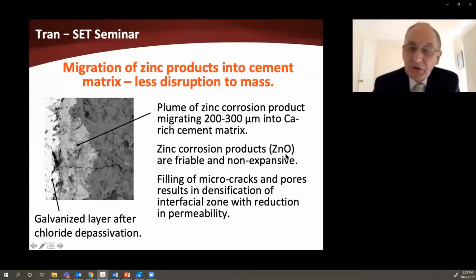Now, these zinc oxide products are friable, they're powdery, they're not loose and voluminous such as iron corrosion products. They're non-expansive, and since they don't precipitate at the surface of the bar, they don't cause distress in the surrounding concrete layer. Some very detailed work has been done on this over the years, and what it's found is that these zinc corrosion products, when they migrate out, fill microcracks, pores and voids in the matrix. They densify what's called the interfacial zone along here, and that effectively reduces the permeability of that zone.